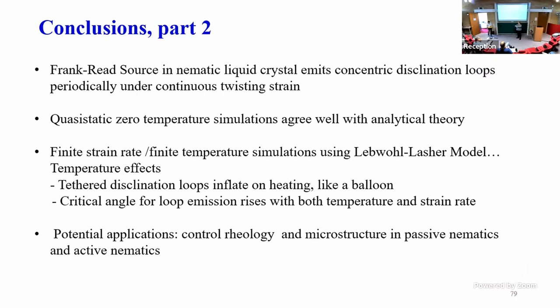Another thing that I think is really interesting is an analogy between soft condensed matter and crystalline solids, the idea of essentially a shear band. Let's imagine an experiment where we had two surfaces with planar anchoring this way and planar anchoring this way, and then we twist them with respect to each other. The stress would build up to a really high level, and then a whole bunch of defects would form and fly everywhere. But if we put a Frank-Read source in the system, as we twist, the defects would always come out in the same place. If we had a whole array of them, then all the disclination motion would be in a single plane. So we would essentially be making a slip band. And that might really change the rheology.